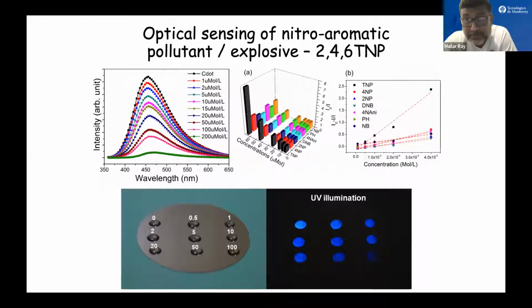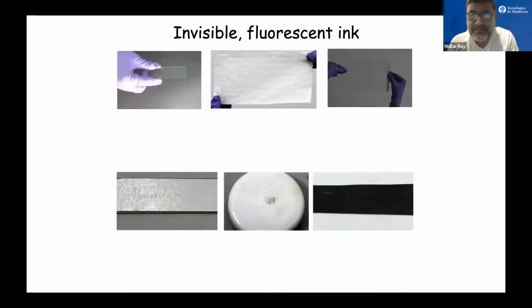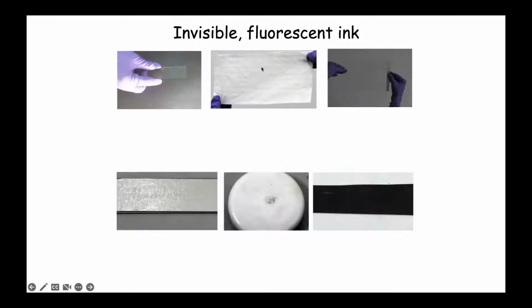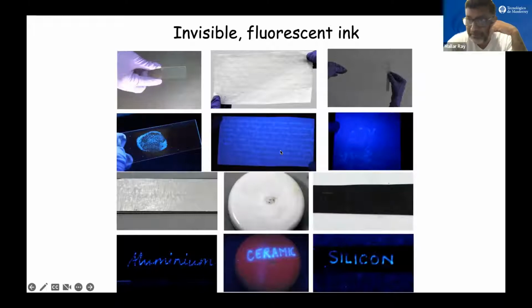We didn't make a device out of it, but we made a device out of something else where we could actually measure the concentration simply by using a paper, like a pH paper, the way you measure pH. We could measure the concentration by looking at the color change, and we can quantify that from the PL spectrum. So that is one very simple application. Another application is making invisible fluorescent ink. Again, many kinds of nanostructures and dyes have been used to make fluorescent ink, but these carbon dots are also exciting materials to make invisible inks. So we can write on a paper, which is not visible under ordinary light, but if you shine UV light, you can see what is written on it. Now that is simple. Some of you who work in this field would know that that's not difficult to do.